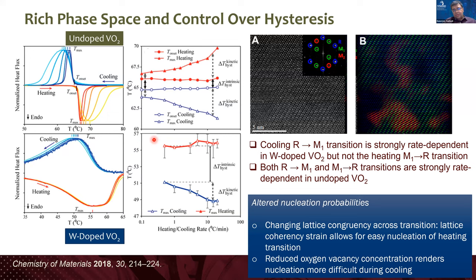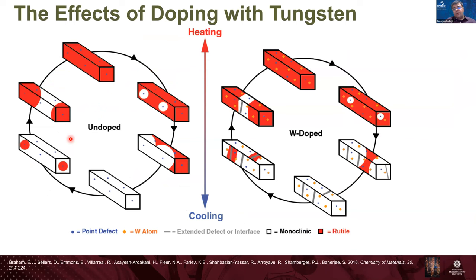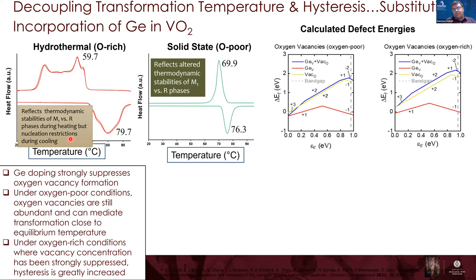And the reason for that is the tetragonal phase, of course, does not have these multiple variants, and because it doesn't have these twin boundaries and phase boundaries, the only place that the transition can nucleate is on oxygen vacancies, and tungsten ends up suppressing oxygen vacancy formation, and so then we end up oftentimes supercooling. And so the effect of doping is really, really interesting. So doping, this is our first indication that doping provides us a means of not just changing the thermodynamic transformation temperature, but also through modulation of the oxygen vacancy concentration, we can change the hysteresis in the material.